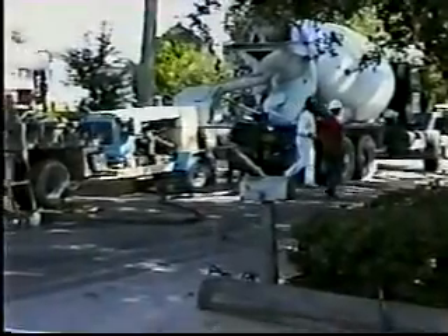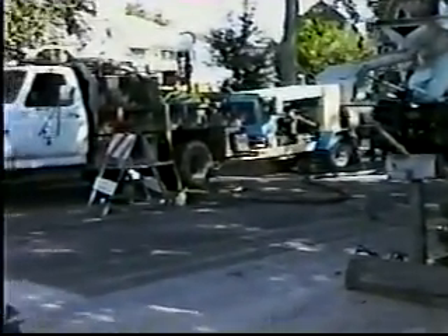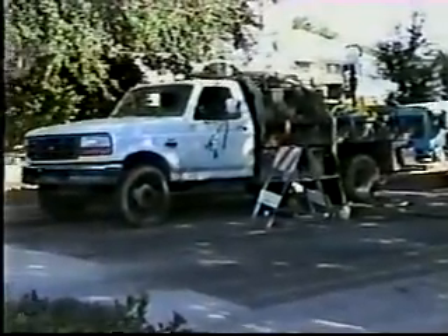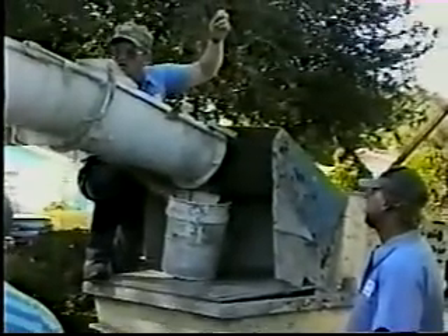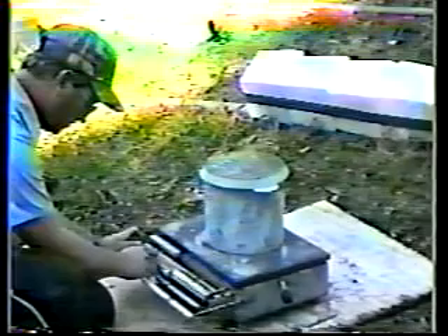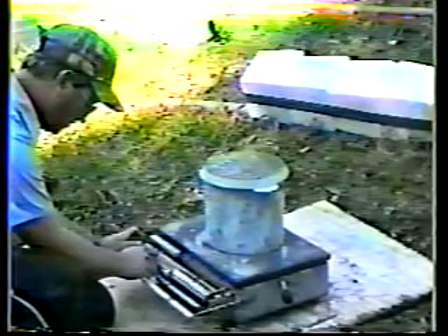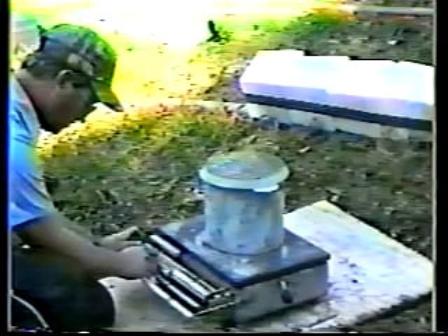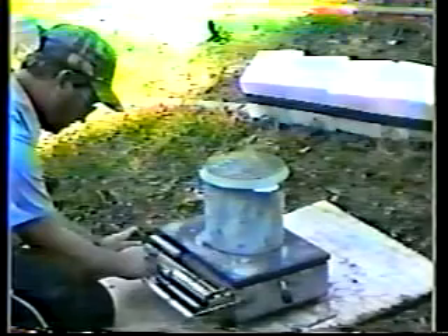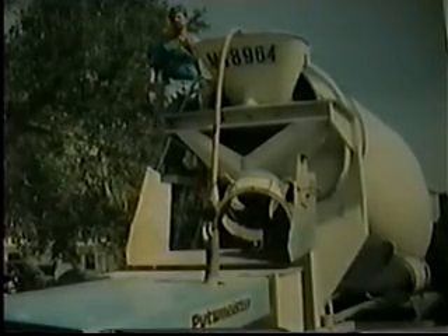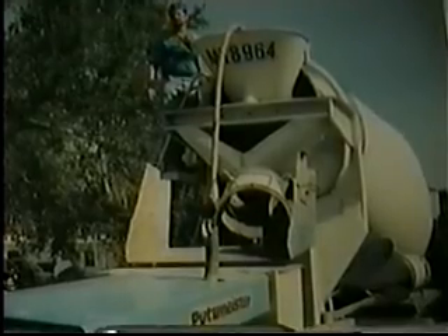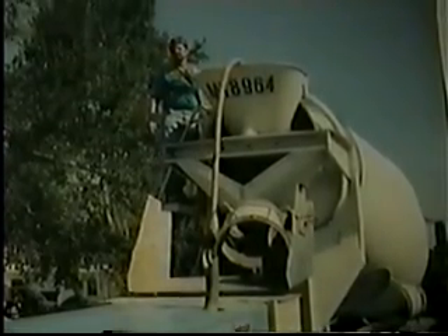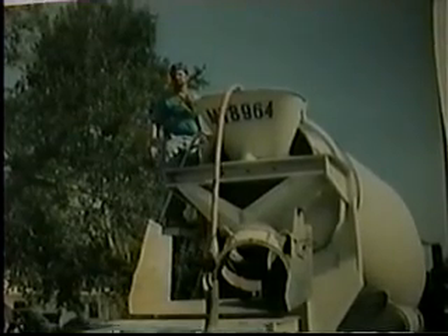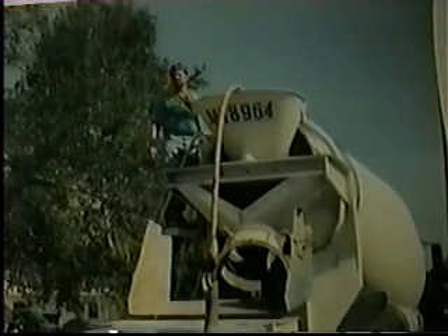This is the ready-mix truck that's delivering cement slurry to the job site. The other equipment you see is support equipment for the grouting operation. Here we're taking a sample of the slurry from the ready-mix truck. The first step in grout quality control is weighing the cement slurry sample, contained in a calibrated container, on a precision laboratory scale to determine its precise specific gravity. Once the slurry weight has been determined, a calculated amount of foaming agent is blended into the slurry in the ready-mix truck. This will reduce the grout density to a specific gravity lower than water.